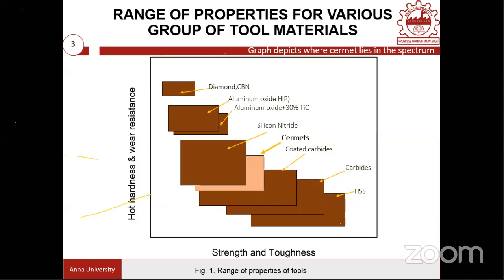Therefore, people moved on to develop a harder material. We should have the ability to cut stronger material, and also have a very high hardness value. So in that aspect, CERMETS are the material which is nowadays used in metal cutting industries, which has very good hardness value compared to carbides, but the toughness value is very poor. Because of this, we cannot employ this tool for interrupted cutting, especially interrupted machining and drilling operations, whereas for turning and fine finishing operations, we can recommend CERMETS. Apart from that, we have silicon nitride, cubic boron nitride, and also diamond, which are recommended only for fine finishing operations. For rough cutting, we are still in need of developing newer cutting tools, especially based on ceramics.